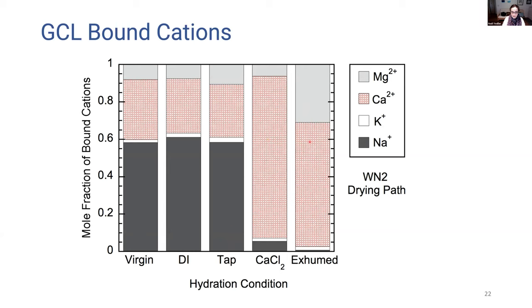This has significant implications for the behavior of the material. For these two cases, we expect this material to have much thinner diffuse double layers, increased hydraulic conductivity, and decreased effectiveness in terms of the barrier function.